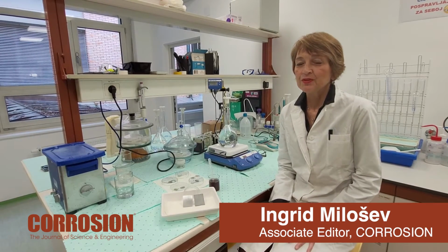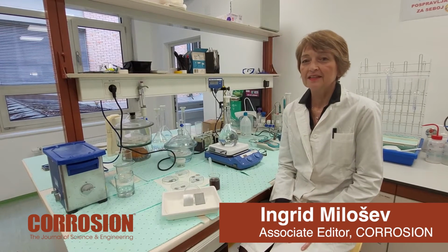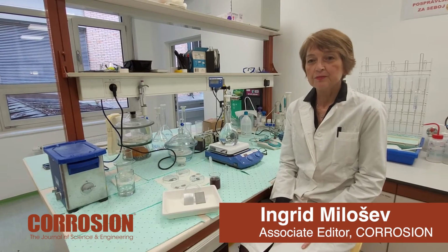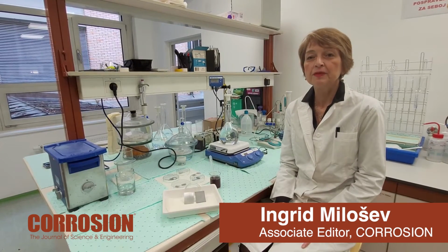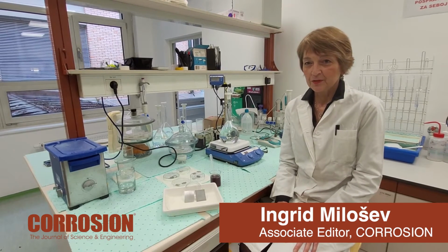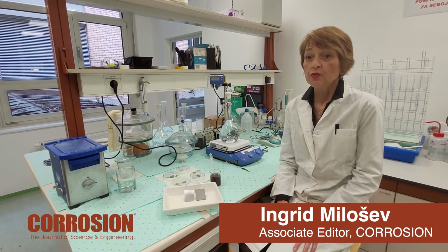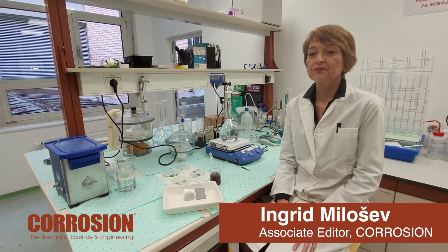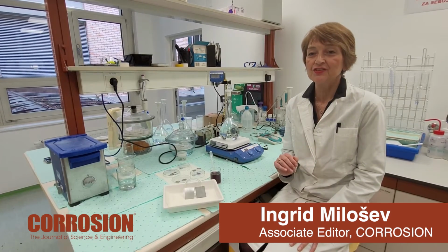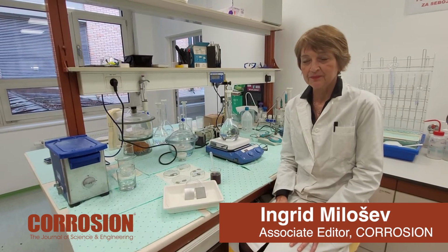So why is that important? Super or ultra-hydrophobic surfaces with a contact angle above 150 degrees bounce the liquid drops, preventing the corrosive electrolyte from remaining at the surface. The authors first modify silica nanoparticles with PDMS or polydimethylsiloxane, which has low surface energy. These hydrophobic particles were then added in different concentrations to epoxy-based solution and deposited on carbon steel.